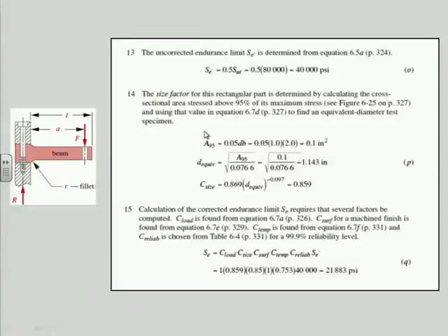I don't recommend using 50%, which would be 1. Whether you use 99.9, 99.99, or 99.999, that's your choice. I think you ought to be up somewhere up there because you saw a scatter that was below the Goodman line in those plots. Some material specimens are not going to deliver the stated, advertised value. So this essentially derates it and says I'm going to draw another line down below that, where 99% of them stay outside, right? Not 50%. And I get a usable endurance limit of 22,000, call it. And I started with 80. That's roughly a quarter, right? That's typical.